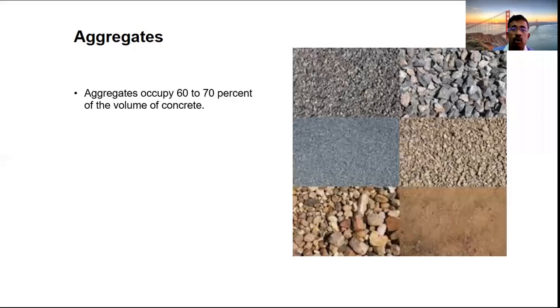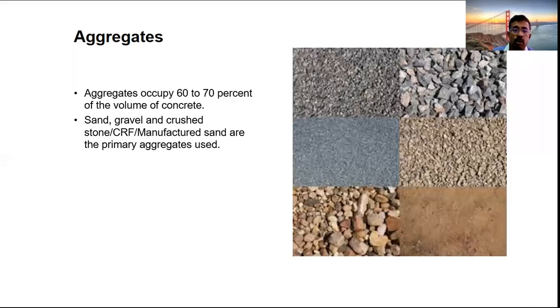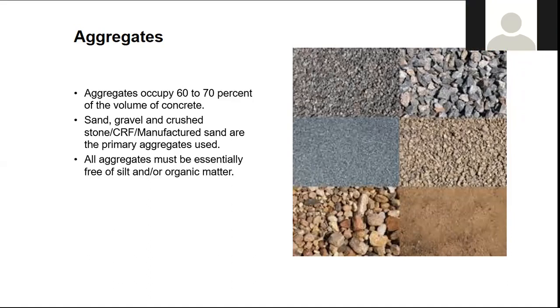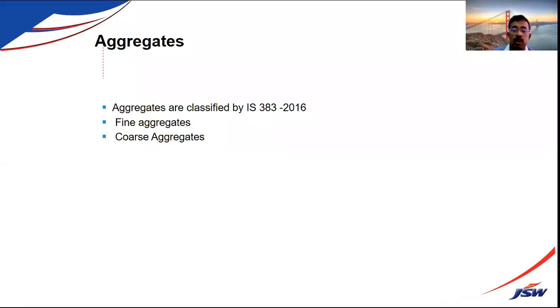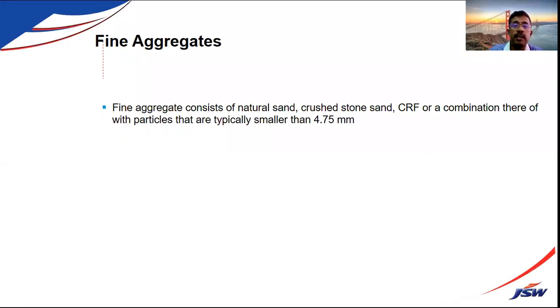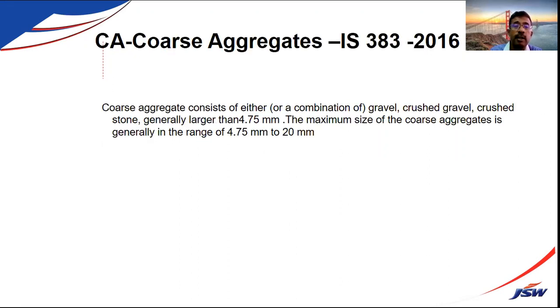So aggregate occupies 60 to 70% of the total volume of concrete, and selection of good quality aggregate is a must to get good quality concrete. So it should be as per IS 383:2016 specifications, coarse aggregates and fine aggregates also. We should properly check before selecting, because fine aggregate plays a very important role in designing the workability of the concrete.